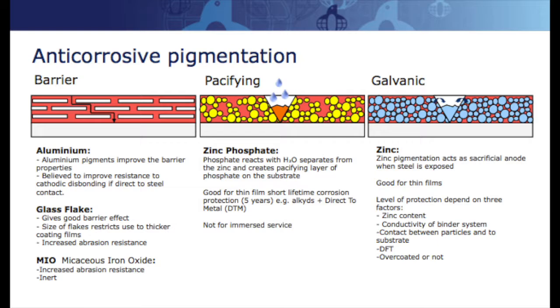And then we come to the zincs. And zinc is a whole topic in itself. That needs a long discussion, because what we're seeing is there's more to zinc than meets the eye when it comes to giving protection. So again, we have standards for zinc. We have standards of how much you need in order to do a good job. The problem is we do it by weight. And weight doesn't actually represent what's going on. And the amount of zinc that's available for giving protection depends on how it's built up into the coating system. So it's much more complicated than, unfortunately, the standards are able to represent.